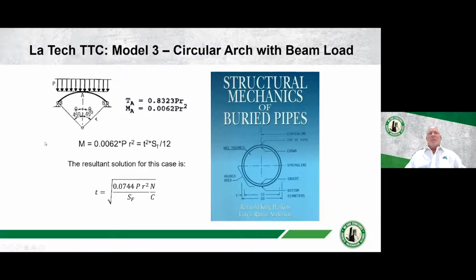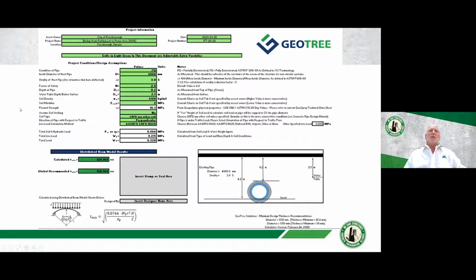Again, this is the formula that we have, so that we know the loading, we know the size of the culvert, we know the flexural strength of the material, so we can calculate a thickness for the material under this specific load for this size of culvert that can be a structurally independent pipe. This just is a spreadsheet that we put together that we can put all our parameters in, and it will come out with a calculated thickness for us, and that's what we're able to use for our design.